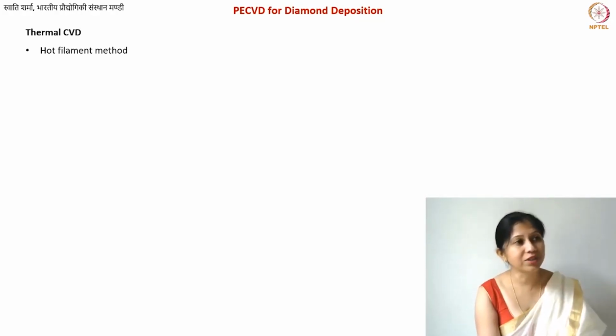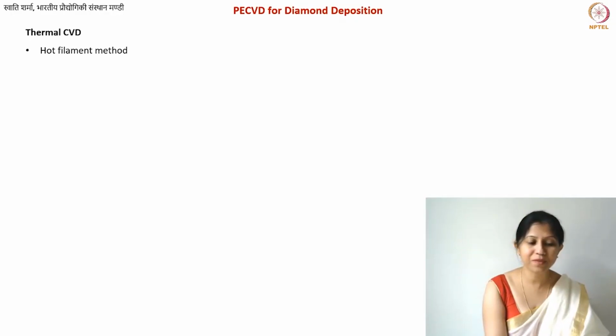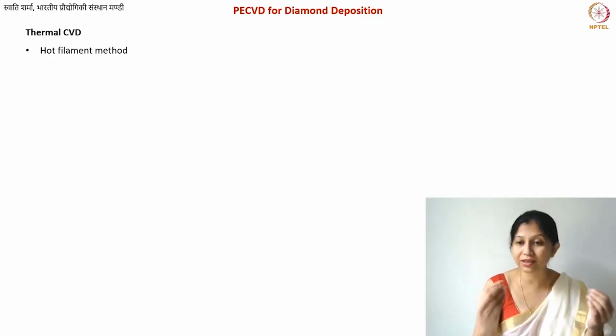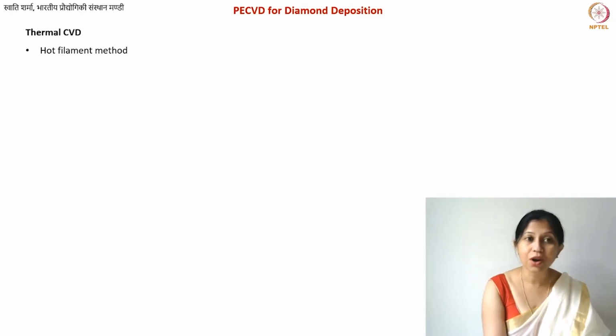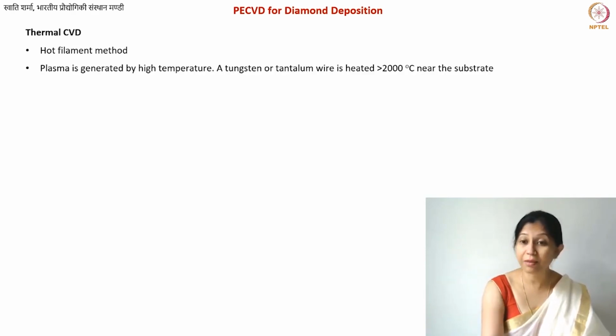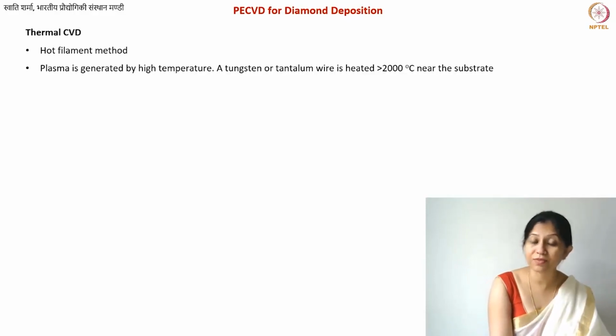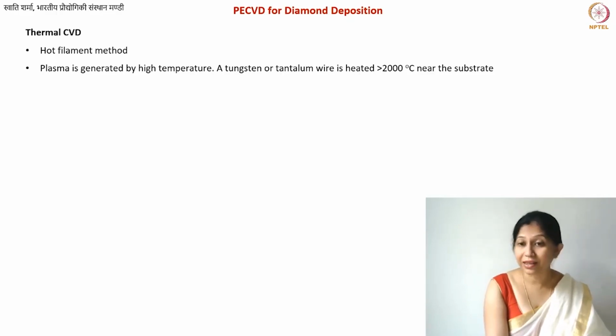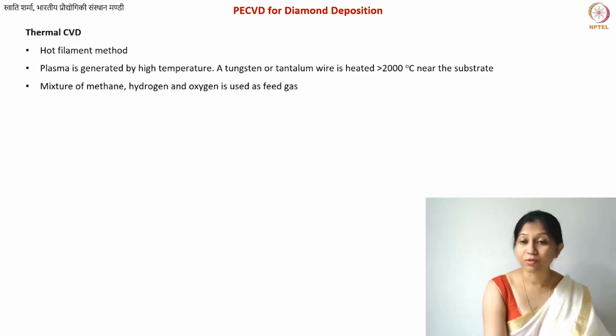So if you want to go to such high temperatures, what you need is some sort of metal which can be joule heated. Number one, the metal or alloy should be able to withstand those temperatures. Also, the filament method works better because filaments are easier to heat using joule heating. So this thermal CVD method is called the hot filament method. The filament or wire is made of tungsten in most cases, or some alloys such as tantalum, and this is heated to above 2000 degrees centigrade.